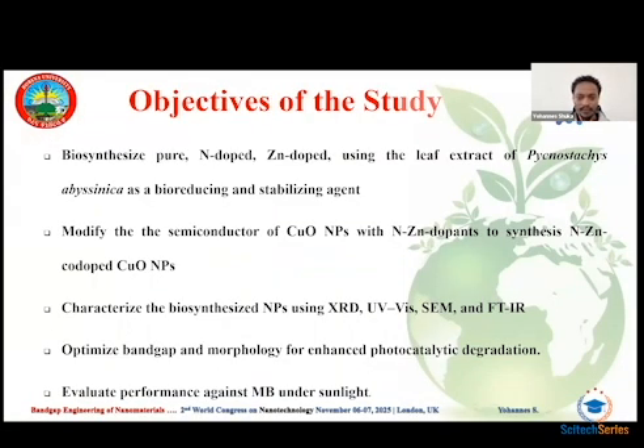So the main objectives of this work are categorized under these specific objectives. The first one is to biosynthesize pure, nitrogen-doped, and zinc-doped copper oxide, using the leaf extract of Pycnostachys abyssinica as a bio-reducing and stabilizing agent. Then, modify the semiconductor copper oxide into nitrogen-zinc-codoped copper oxide. Then, characterize the biosynthesized nanoparticles by using advanced analytical techniques, and optimize band gap and morphology for enhanced photocatalytic degradation. The final one is to evaluate performance against methyl violet under sunlight radiation.